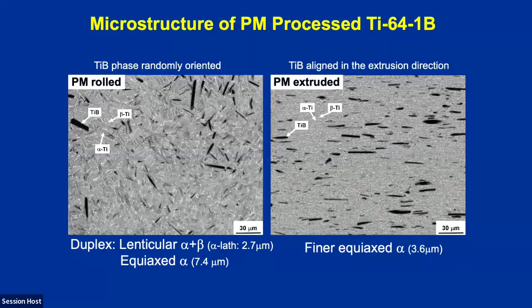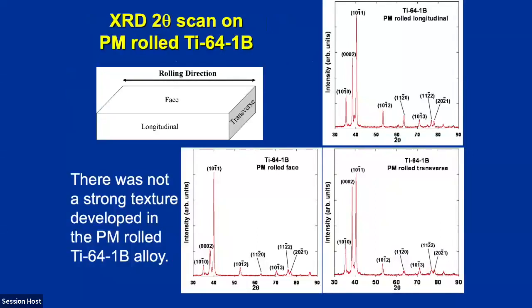And this, we're going to find out later, is the stiffest direction for the titanium boride phase, which results in even higher stiffening than when you have a randomly oriented whisker. And roughly the volume fraction of the titanium boride phase is the same in both microstructures.